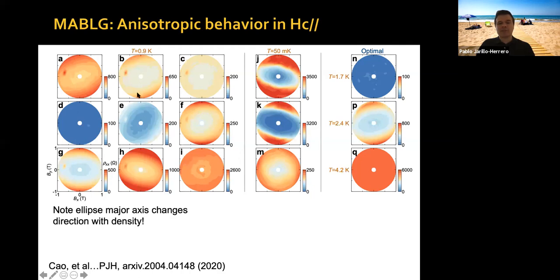We choose the temperature here. We have a vector magnet in our cryostat with a maximum in-plane field of 1 Tesla. So we have to choose an intermediate temperature so that we can see the ellipses at the different dopings, because TC varies. But then we can go to base temperature, or intermediate, and see the strength of the ellipses at different dopings. We can go to optimal doping where, within one Tesla, we don't see anything because it's always superconducting, even at one Kelvin, but then we increase to 2 Kelvin and then we see the ellipse. We can vary all these parameters.